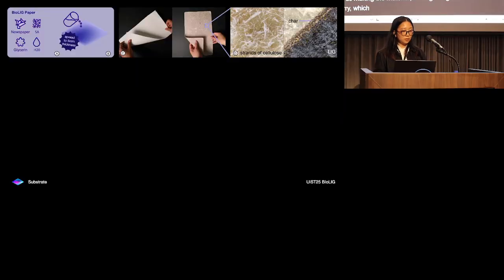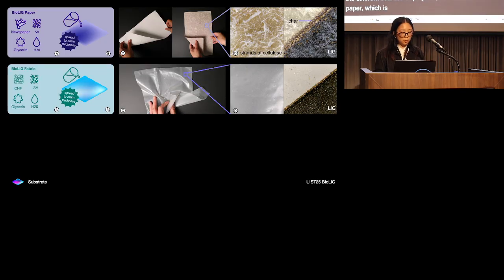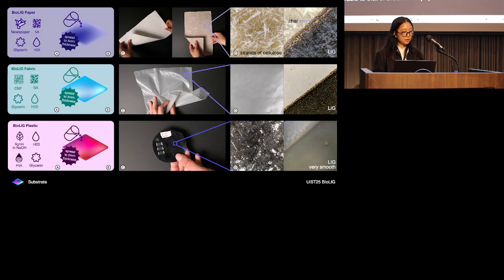So iterating on the different sources of polymer, we created 3 sheet materials: the BioLIG paper, which is a paper-like robust material with tensile strength comparable to that of brown kraft paper; the BioLIG fabric, which is a fabric-like soft flexible material based on cellulose nanofibers; and the BioLIG plastic, which contains lignin and PVA, making it rigid and more water repellent. In the middle column, you can see the material samples, and on the rightmost column, you can see the material both before and after graphitization under 250 times magnification.